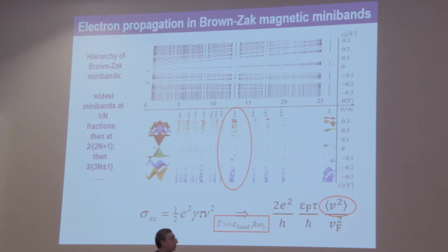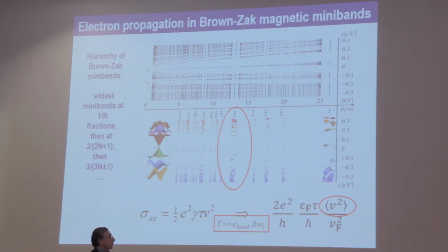We think in terms of electrons propagating not just in one of those minibands, but in one or the other across the temperature energy range, which is covered by the Boltzmann constant multiplied by the temperature in the system. And then we look at what the conductivity is determined by, the Einstein relation, where the typical group velocity of electrons that move in the minibands is now taken as an average of several minibands in the spectrum, having in mind that we deal with high temperatures.